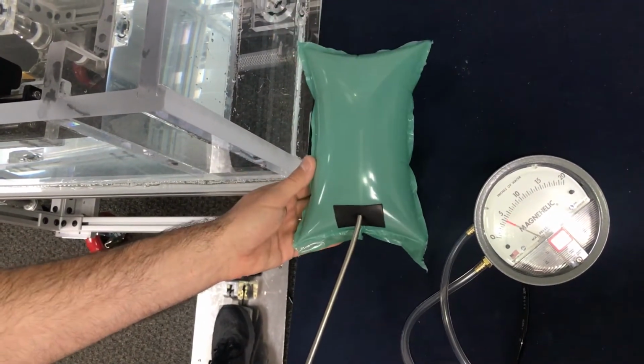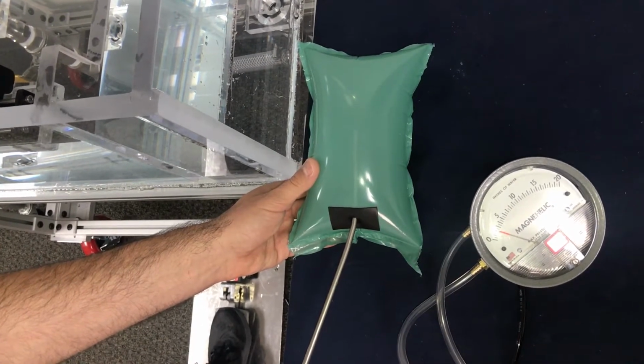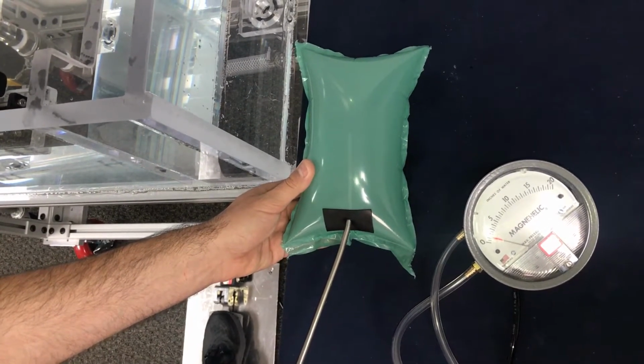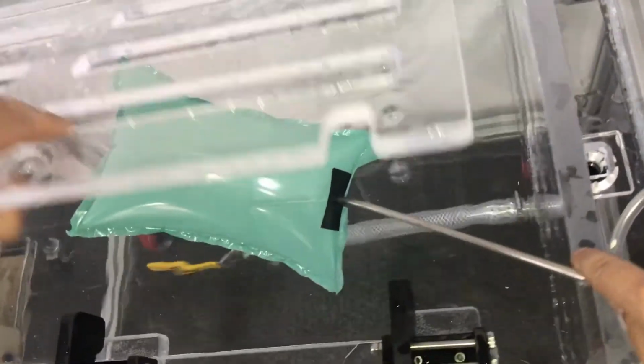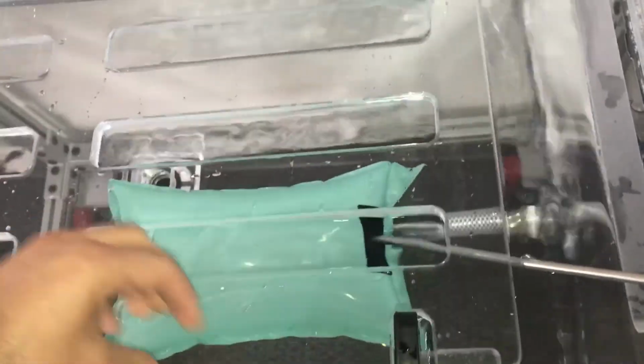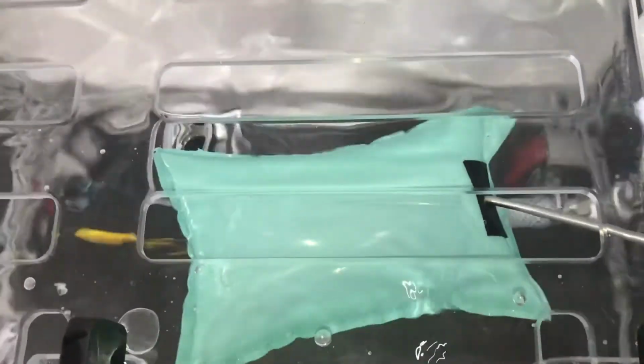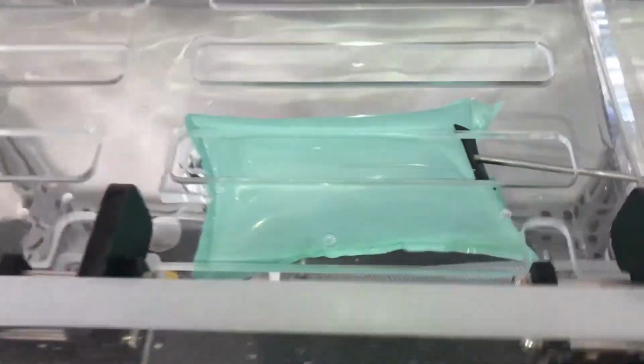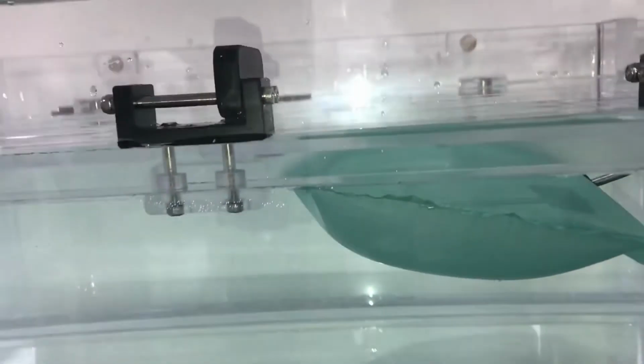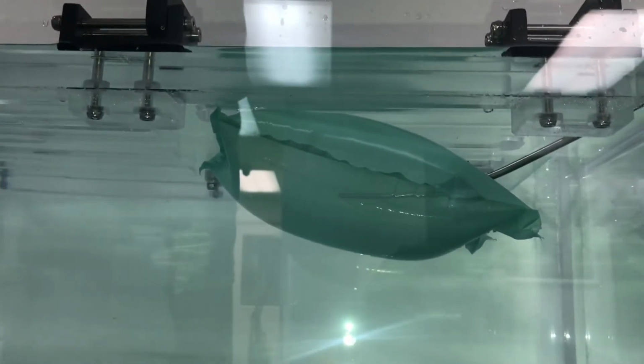And you will notice that the magnehelic gauge is going to drop. The reason that it will drop is because that indicates that your package is fully inflated. Now place them into your water tank. Of course, close the lid and then lock the sliding locks. And then you will hold the foot pedal, and you will look for bubbles.